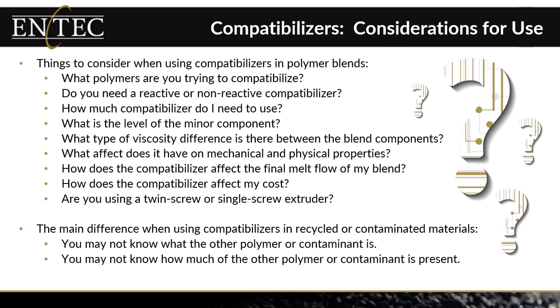How does the compatibilizer affect the final melt flow? Once again, this is a big one, and this is where I see a lot of the challenges, especially when a reactive compatibilizer is the best choice for the polymers you're blending. But once again, it negatively affects the melt flow of your final blend. And there are some things that we can do. There are some tricks that we have that can help with that while still getting good compatibilization, but trying to minimize the negative reduction in melt flow of your final compound.